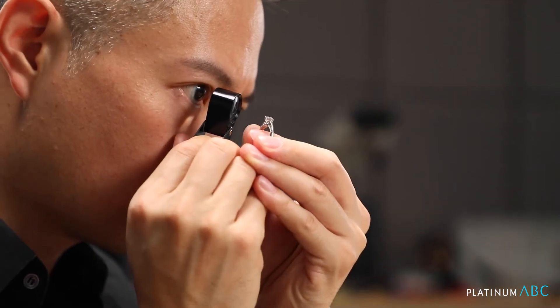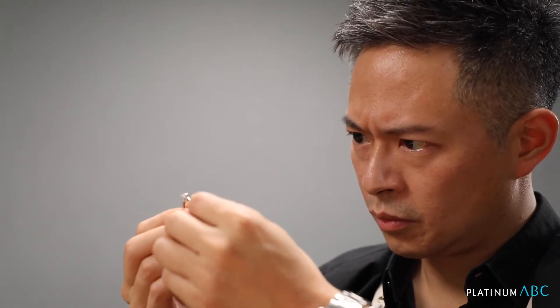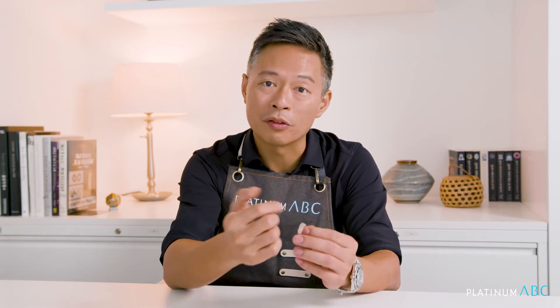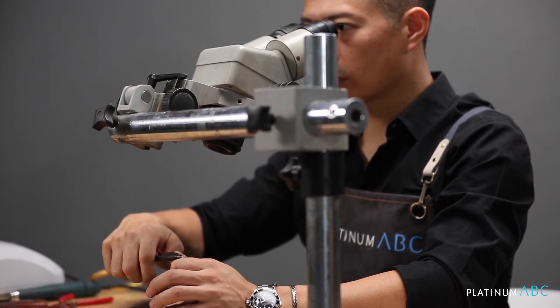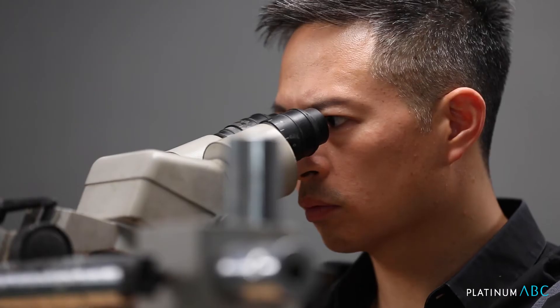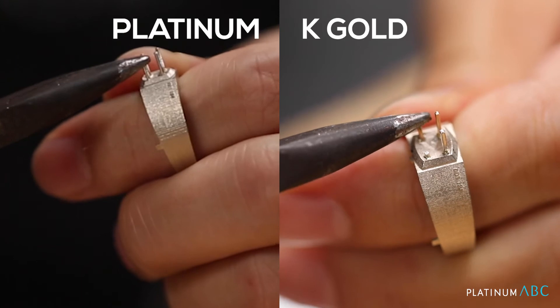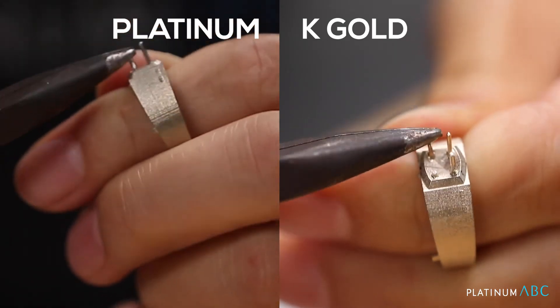Another really big difference between platinum and K-Gold is how the tenacity of platinum makes a difference for long-term ownership and long-term wearing. Here we're going to do a very simple experiment. Two of these wires are in platinum and two of them are in K-Gold. I'm going to take a pair of pliers and bend the prongs back and forth to see how many times the metal can be bent. This mimics setting and resetting of diamonds, which sometimes happens in production or in servicing, and also damage from daily wearing — for example, if the prong is snagged or if the ring is banged against something very hard.